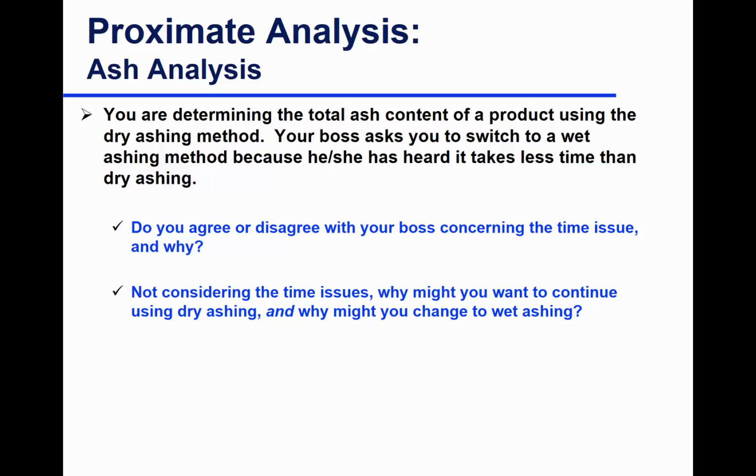Well, that is correct, but if you want to determine percent total ash, would the wet ashing give you percent total ash? No. If you're after determining percent total ash, you cannot use wet ashing. It won't tell you percent ash. But if your purpose is for mineral analysis, then yeah, you can consider that, if that's more important than your time standing 2 hours working on a corrosive, highly involved method.